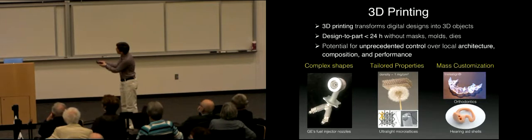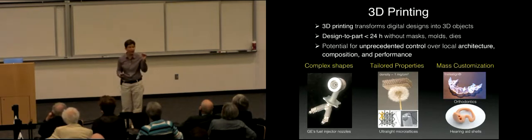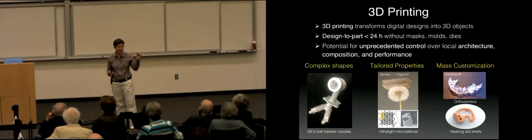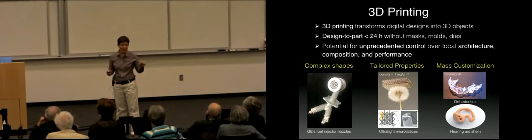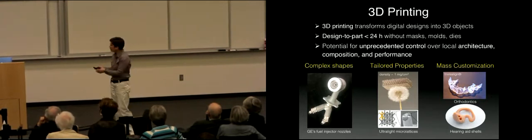And what you're looking at here is a metallic lattice. And this is a component of that lattice under higher magnification. It's metal, it has thin walls, 100 nanometers thick. Just to give you a sense, the width of a human hair is 0.1 millimeters. So this is many orders of magnitude thinner.